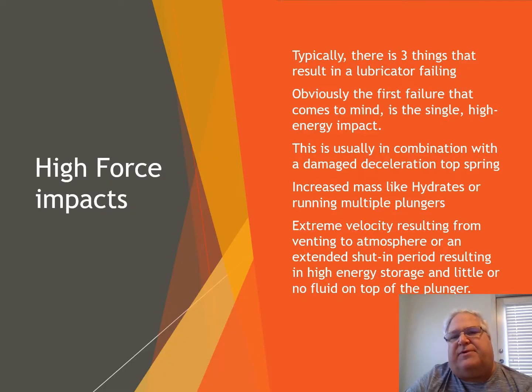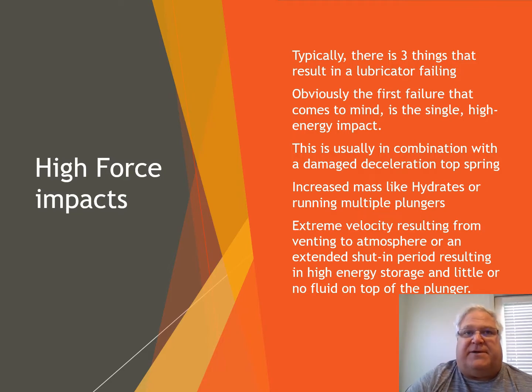So there's typically three things that we've found that result in lubricators failing. Obviously, the first failure that might come to mind is that single real high energy impact, which is usually caused by a combination of your top spring being damaged, so there's no absorption there, and somebody has taken the well to atmosphere to unload it, or there's a hydrate that forms and they pull it to atmosphere, and you get these extremely high velocities resulting in super high kinetic energies being put into the lubricator, which can stretch and damage the lubricator.